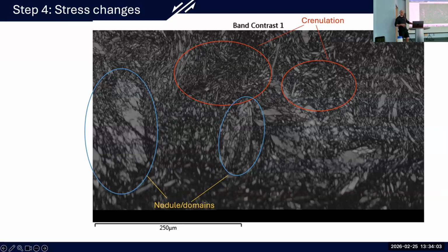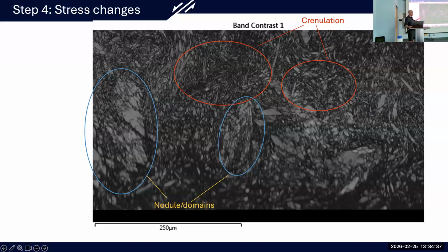in small domains. And the issue here is, as I was going through this scheme, you imagine the entire rock undergoing that transformation. But as I mentioned, stress fields are very heterogeneous within the shear zone and can even vary at a local scale. And there can be reasons for small domains to be preserved, stress shadows, pressure shadows as things evolve. And so ultimately, it's this constant changing of stress fields during deformation, during mineral growth, that favors this very complex